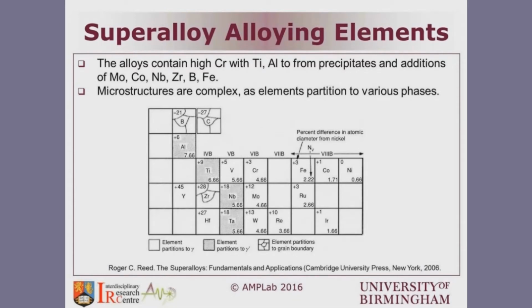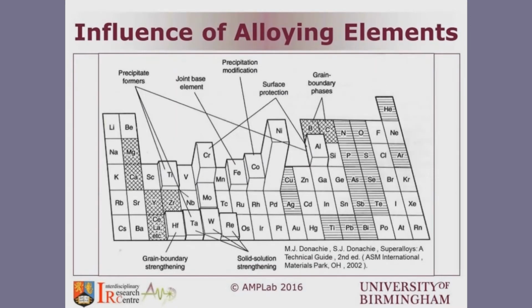As a matter of fact, the way that the microstructure behaves is rather complex, since some of these elements partition to specific phases. For instance, boron can partition to the grain boundary. Titanium and aluminium partition to the gamma prime phase, which is the strengthening phase in nickel superalloys. Some other materials like niobium partition also to the gamma prime and gamma double prime. So the role of the different elements can be quite difficult, and that adds to the complexity of nickel superalloys in general, and also the complexity of how we think about them as a material to be used for additive manufacturing.